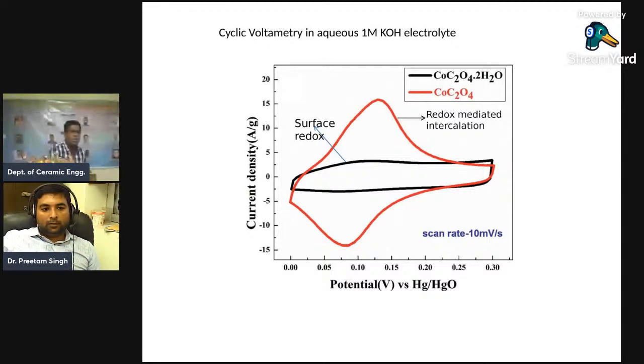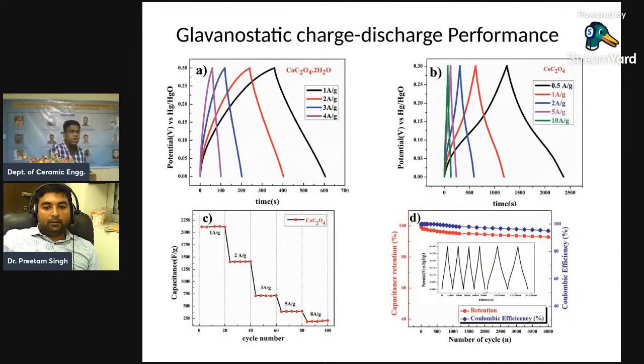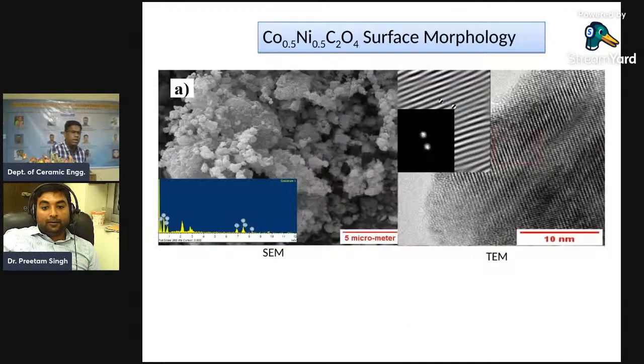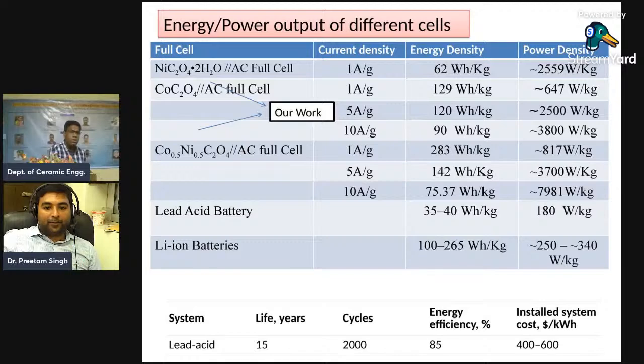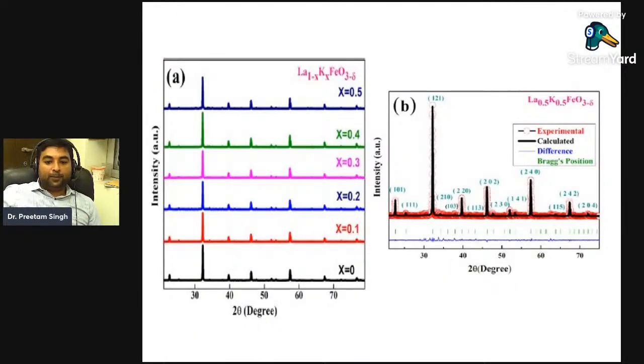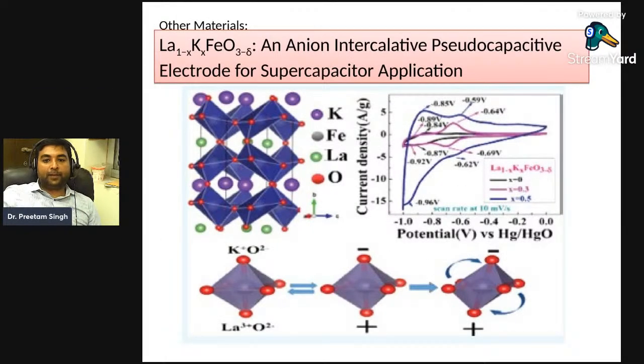You mentioned the iron +4/+3 and +3/+2 redox couples in that oxide supercapacitor, but actually there wasn't any peak. So how do you justify that reaction? No, peaks are there. That's what I'm just going to show you. See, these peaks are there. You can see this redox peak, like at 0.85 volt and minus 0.59 volt. However, the surface domination is very high, so that's why you cannot distinguish them as very distinctive peaks, but the peaks are there.